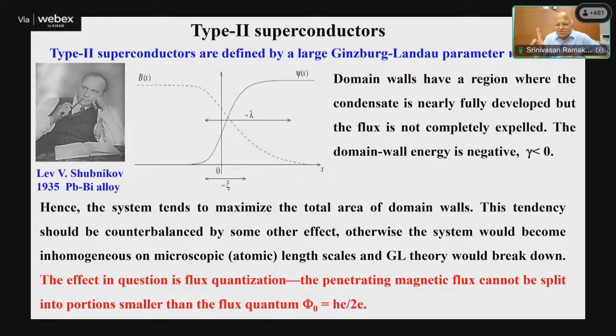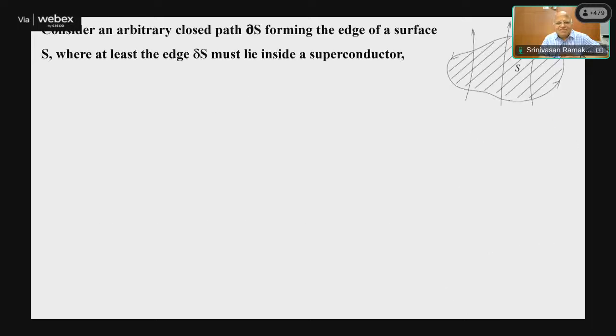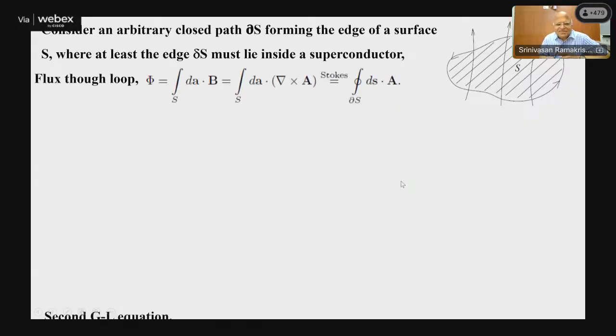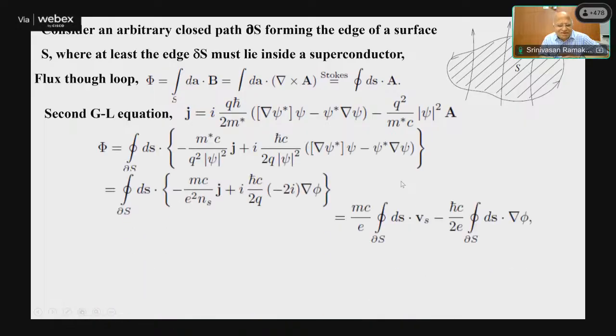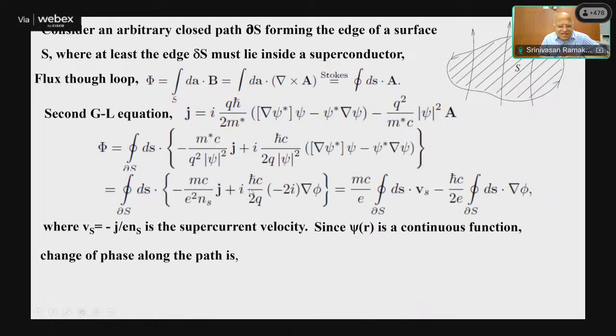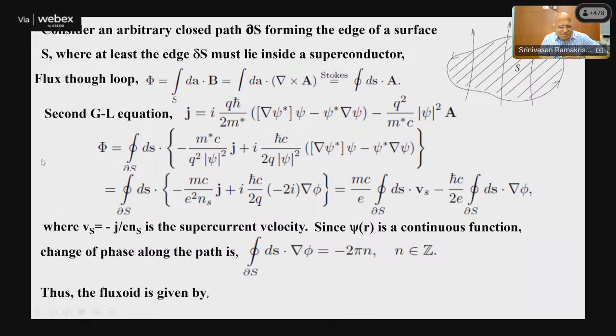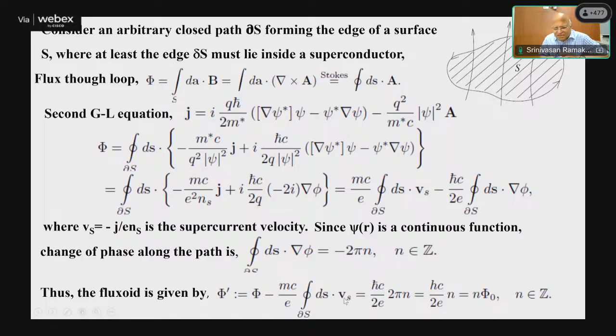So we said that there is a ring where we see a flux quantization, and this penetrating magnetic flux cannot be smaller than the flux quantum. So what people did was to show that the flux inside this, which they call a fluxoid, is given by this expression: the applied flux minus this supercurrent expulsion of the magnetic flux. This is again an integral value of the flux quantum.